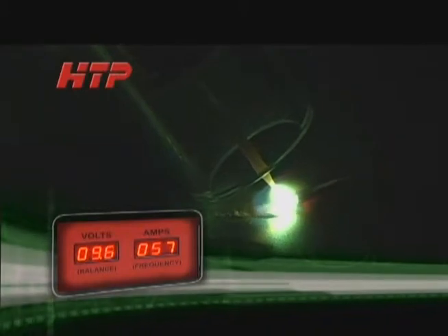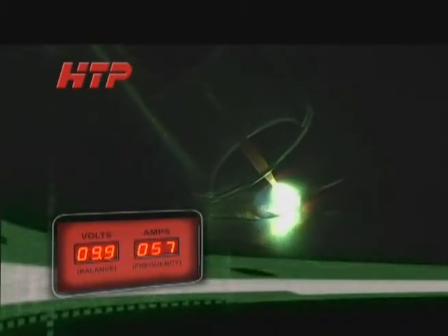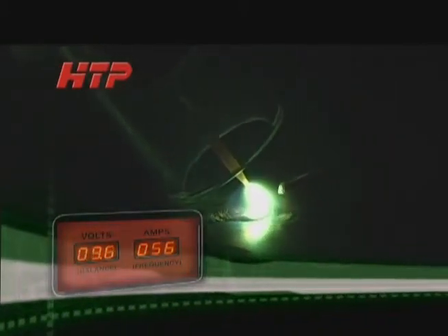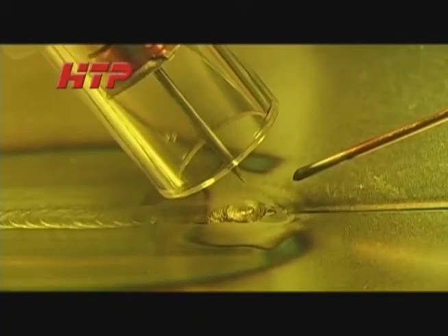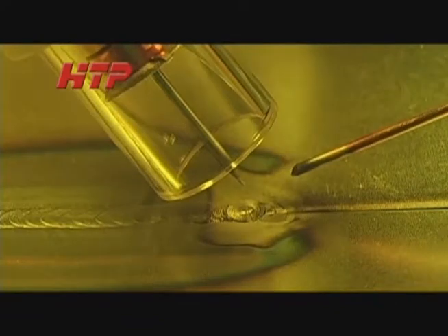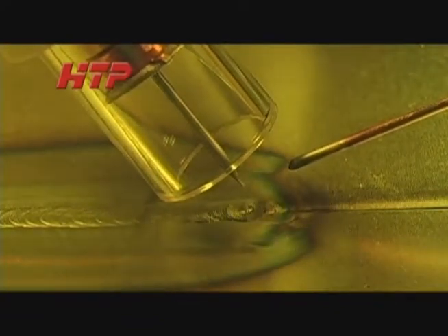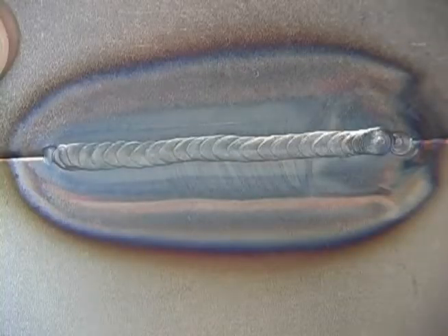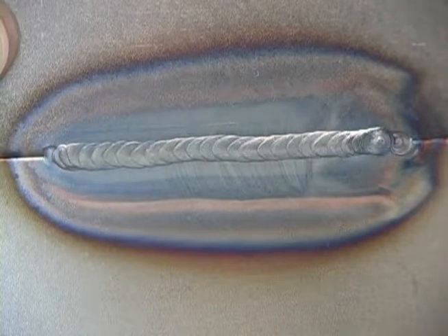When you get to the end of the weld, gradually back off on the pedal until the arc extinguishes, and remember to leave the torch in the same position until the post gas flow stops. Look at this beautiful weld. You have an extremely consistent bead width with that very nice row of dimes look.